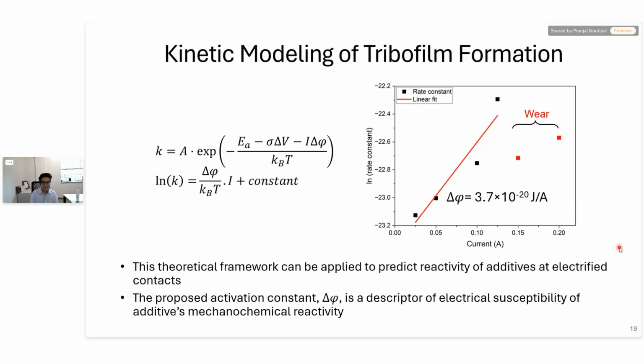So the higher the value of delta phi, the more susceptible the lubricant additive would be to electric fields. In other words, the higher the delta phi, the higher the current-induced acceleration of mechanochemical reactions. And this will help us model the kinetics of mechanochemical reactions under electric fields. In the future, we envision we can capture the value of delta phi for a wide range of additives with different molecular structures. And these values will provide fundamental insights into the molecular mechanisms by which electric fields affect